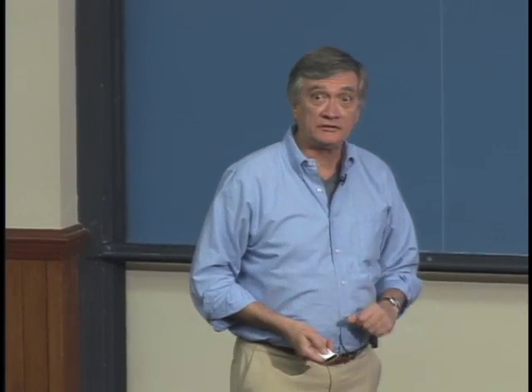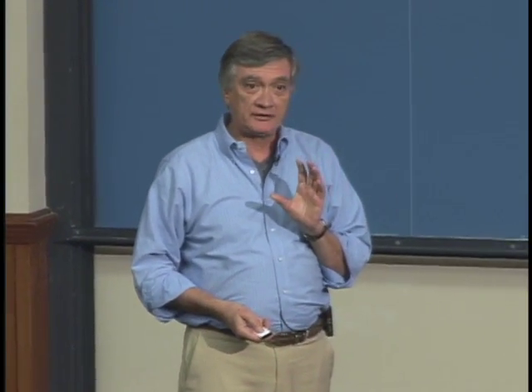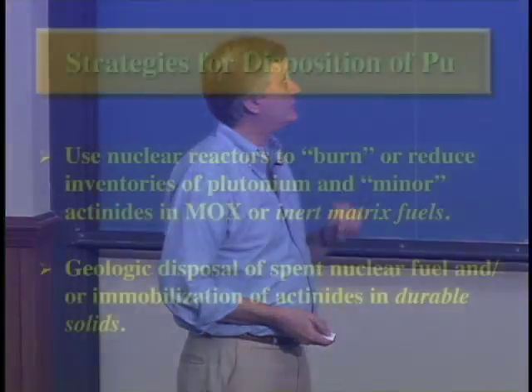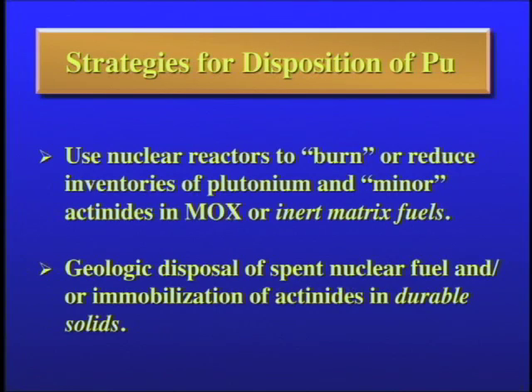Now, in the broadest sense, there are two strategies for handling this plutonium. The nuclear strategy involves getting it back into reactors to burn down that inventory and take advantage of the energy content of that plutonium. You get it back into the reactor by mixing it with more uranium, a mixed oxide fuel, MOX, and put it in the reactor. But of course, when you mix something with uranium, you put that uranium back in the reactor and it begins to make plutonium. So the MOX solution leaves you about where you started when you finally pull out the MOX fuel.